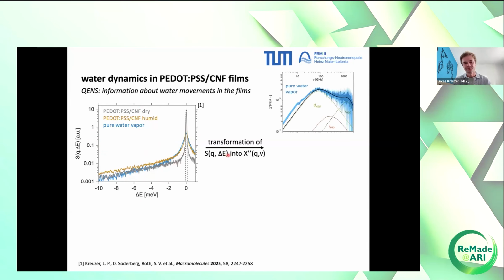We can transform this dynamic structure factor into the dynamic part of the susceptibility. Now, susceptibility measures how a system or films respond to an external perturbation. In this case, the external perturbation would be the scattering event with a neutron. And then you have the susceptibility as a function of frequency. So frequency is just another energy scale. And it's a very convenient way of plotting or aligning the different dynamical contributions of water, because water is what we see. We set the energy range so that we follow along the water movement.